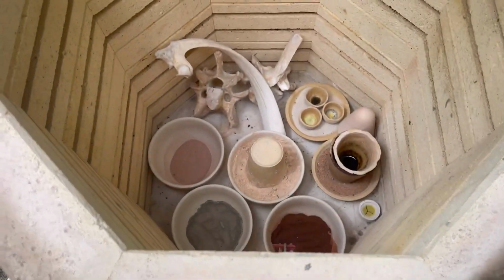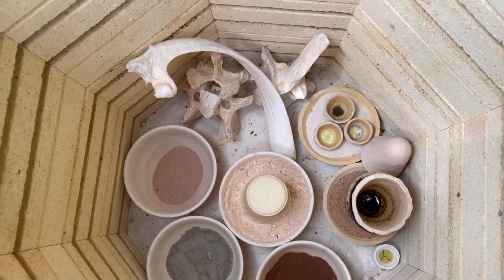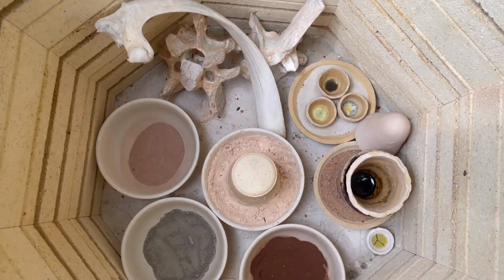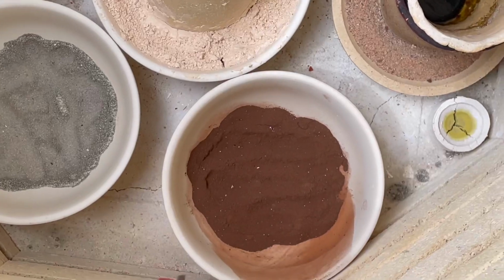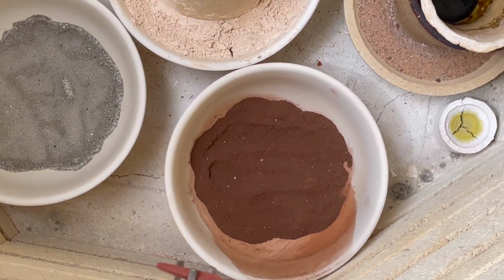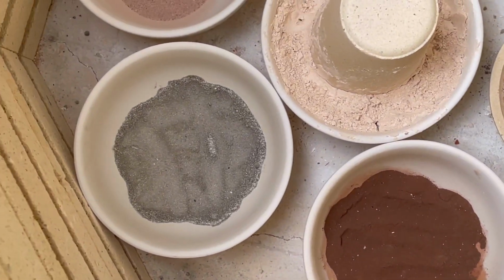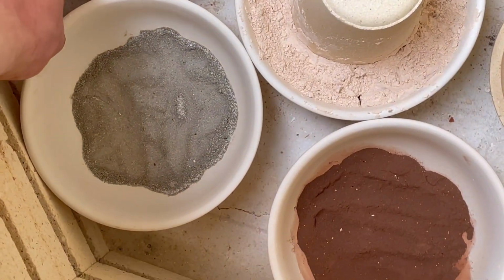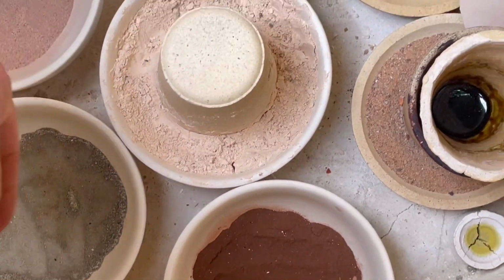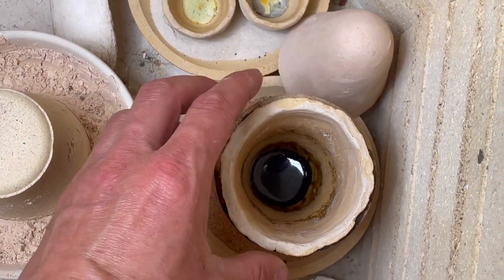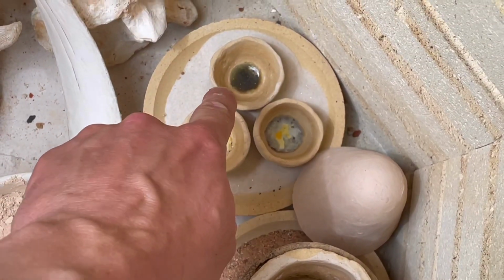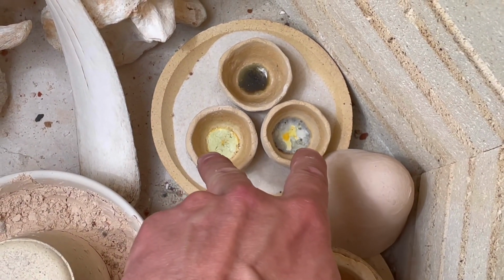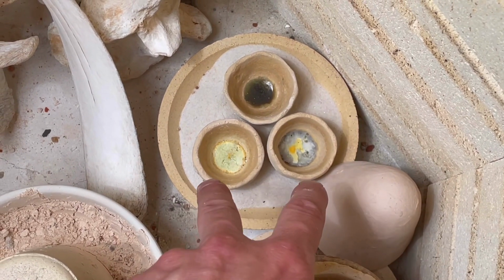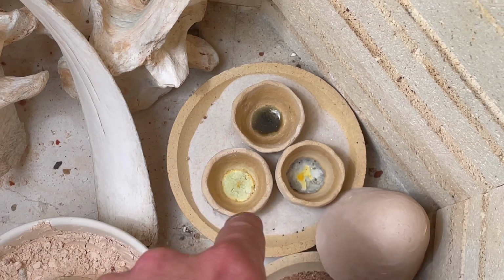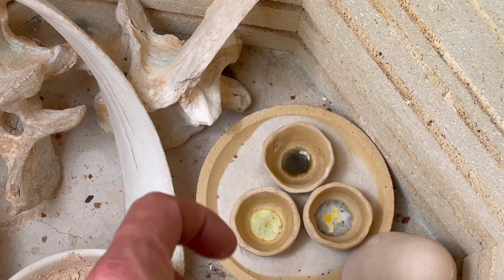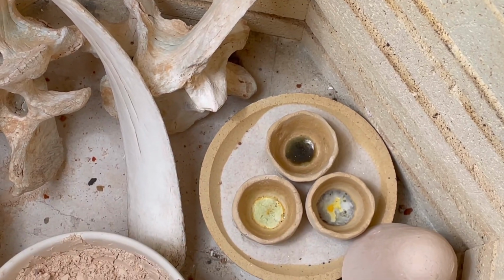Okay, so this finished cooking. I let it cool down overnight. Let's see what we got. So the sulfide ore is now turned red. Might have had some organics that burned off. The limestone one appears to be well cooked. And these, the test samples I was doing, that one worked, that one's good, those two, I'm probably going to have to reheat and adjust the recipe or try again. See, that's why I did that test, so I am only doing it on a small scale rather than a full crucible worth of material.